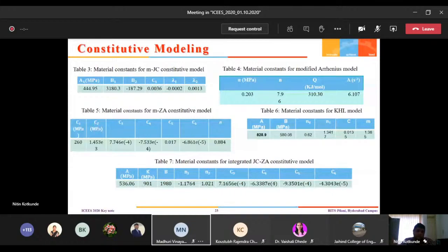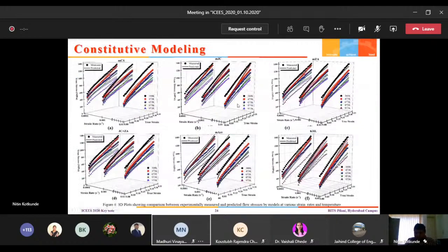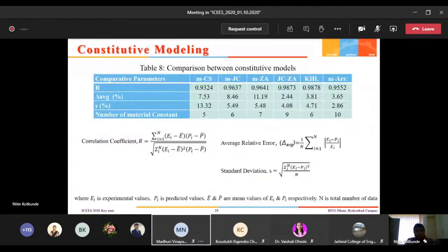So this is the comparison of flow stress graphs. This is a 3D diagram we have plotted. In this diagram, if you see here, it has been plotted for true stress, strain rate, temperature and strain values. Usually the best predicted model can be determined based on the correlation coefficient, average relative error, and standard deviation. These are the 3 statistical parameters we use to calculate the suitability of the model for a particular material. So we have calculated that, and this R value is nothing but the correlation coefficient. We use this equation to calculate it, and the average relative error and its standard deviation we also calculate.